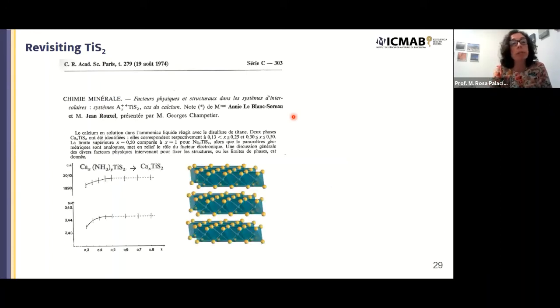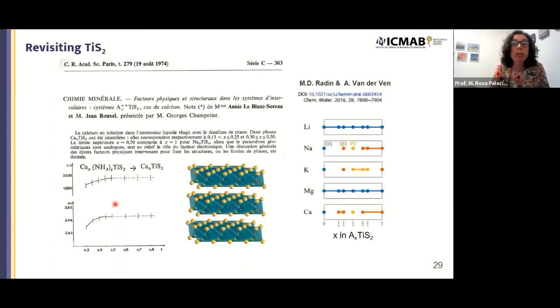This compound has been studied a lot from the early days of intercalation. And here there is a paper from 1974 from the group of Jean Rouxel in Nantes, where they were able to intercalate calcium in TiS2 by immersing this compound in a solution of calcium in liquid ammonia. At the beginning, ammonia was co-intercalated with calcium, but then by gently heating, they were able to remove the ammonia. And then they even suggest some crystal structure for calcium between the layers that they believe is octahedral.